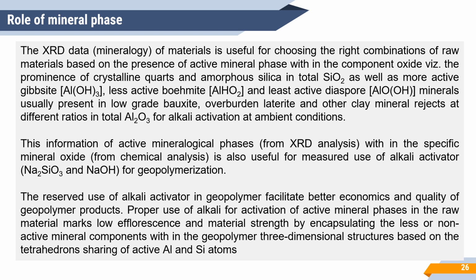This information of active mineralogical phases within the specific mineral oxide is also useful for measured use of alkali activator, that is a combination of sodium silicate and sodium hydroxide for geopolymerization. The reserved use of alkali activator in geopolymer facilitates better economics and quality of the geopolymer product. Proper use of alkali for activation of active mineral phases in the raw material marks low efflorescence and material strength by encapsulating the less or non-active mineral phases or mineral components within the geopolymer three-dimensional structures based on the tetrahedron sharing of active alumina and silicon atoms.